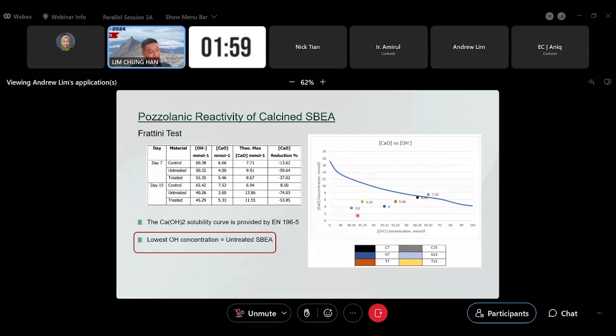That's because the x-axis is measuring the OH concentration remaining. So as you can see, this 3.6 here is the one that has the least amount of calcium hydroxide left, so that indicates highest reactivity. This light blue color corresponds to U15, which is the untreated SBA again. So this test is telling us the untreated SBA is giving us the best reactivity.